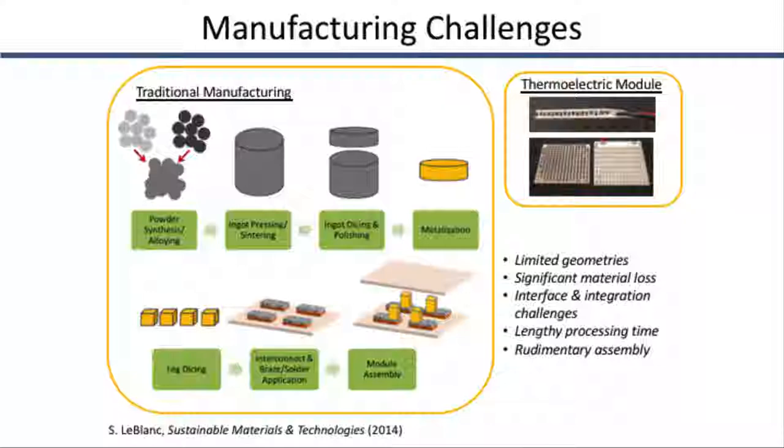Moreover, one of the cost drivers for these devices and the limitations to getting them into applications is that these materials are quite expensive. Many of them use rare earth elements. In this manufacturing process, when you make it this way, you throw away over 50% of that really expensive thermoelectric material, which, again, is shocking. And then we do this very mechanical component of taking legs and attaching them with metal onto electrical shunts. So this interface is an electrical and thermal interface that completely degrades our device performance and doesn't enable us to effectively integrate our materials into the devices.